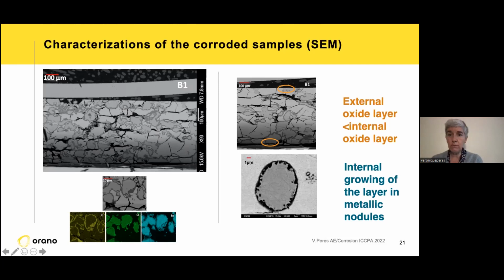That means that we have an internal growth of the layer in the metallic, in the stainless steel particle, and then we have a catastrophic oxidation of this particle inside the composite. And we produce some chromium oxide and many iron oxide layers, which lead to this crack system, and with a high mass gain, much more than the powder one.